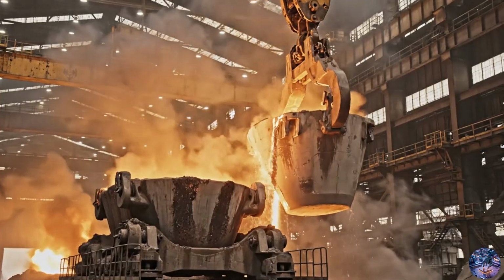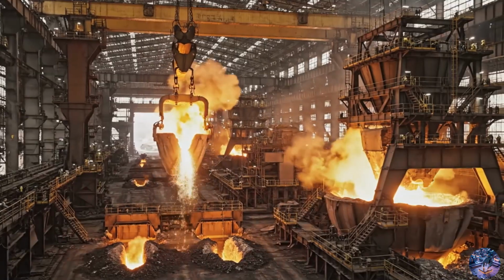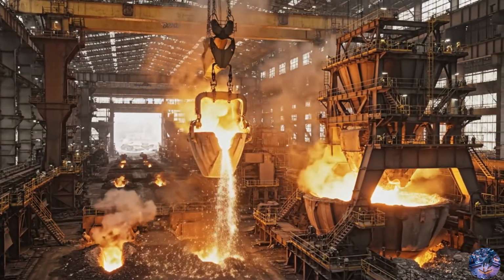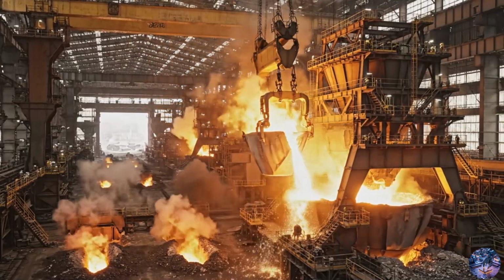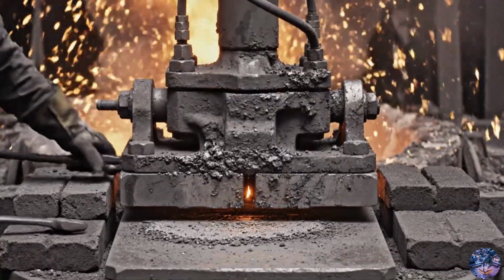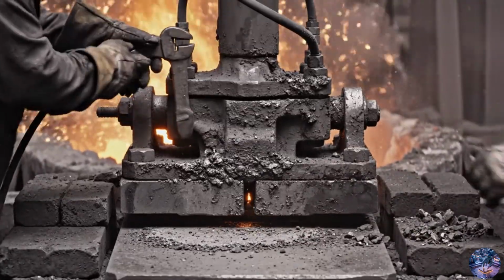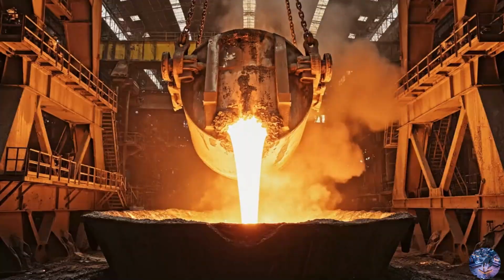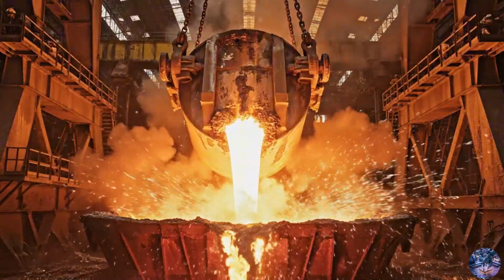Inside the mold, the outer skin of the steel solidifies instantly while the core stays liquid. The mold vibrates rapidly. Oscillation prevents the red-hot skin from sticking to the copper. Water sprays blast the emerging strand, turning the red-hot metal into a solid structure.